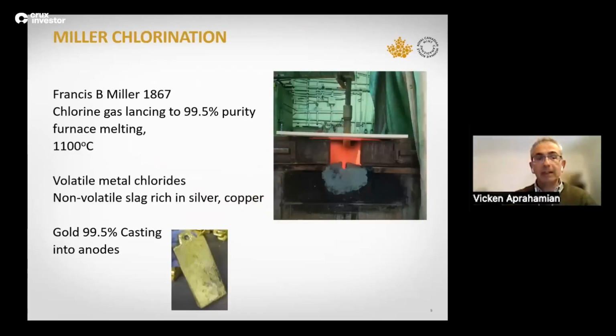So Miller chlorination is a process that is over 150 years old, invented by Francis B. Miller in the 1860s. And again, you see the induction furnace system with a chlorine lance introduced. This all happens at high temperature. I'm mentioning 1100 Celsius, but it is an exothermic reaction and needs to be controlled. Again, the volatile metal chlorides fume off, and a non-volatile slag rich in silver is recovered and skimmed away for processing. And the lower picture shows the cast anodes, which are basically 99.5% in general, but they can be slightly impure, anywhere between 95 and 99.5.